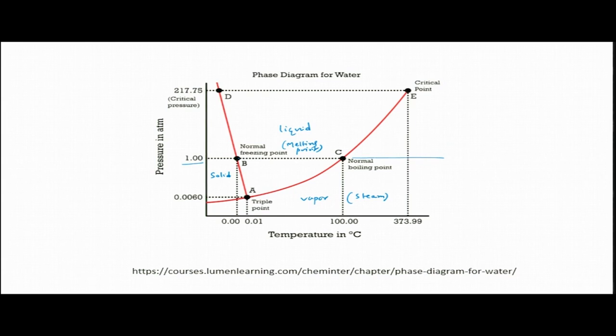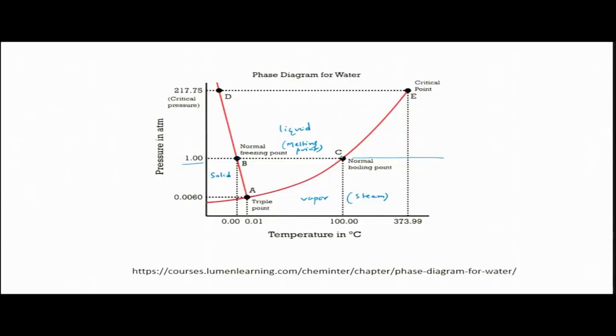The thermodynamic melting point and freezing point would differ a little bit when we look at practical situations. For example, during freezing, it does not freeze at that particular thermodynamic melting point, because when it freezes, we need to create an interface, and because the solid is forming, that interface needs extra energy. So, by cooling we get the undercooling effect, that is del T, and that del T gives you the volume free energy that is available for doing work, and that work is done to create those interfaces, because an interface always carries positive energy, we call it interfacial energy, fine. So, the practical freezing point would be a little less than the actual thermodynamic melting point. But this is the thermodynamic melting point, and this is the thermodynamic boiling point, fine.